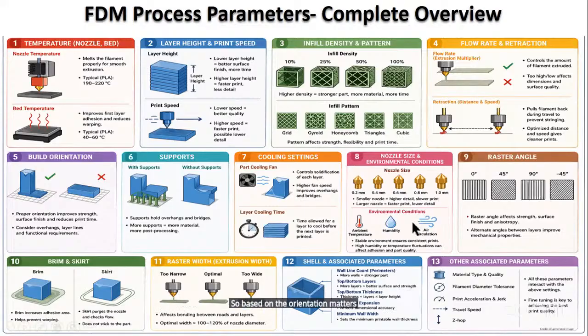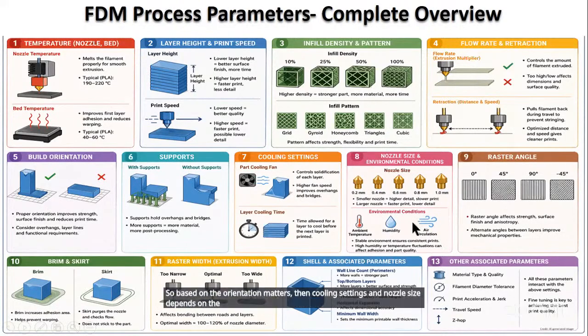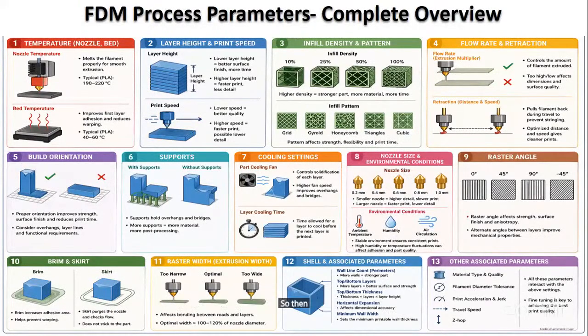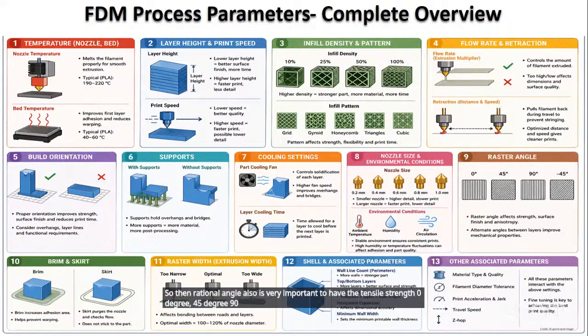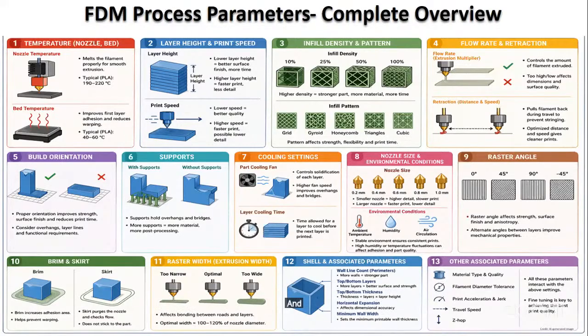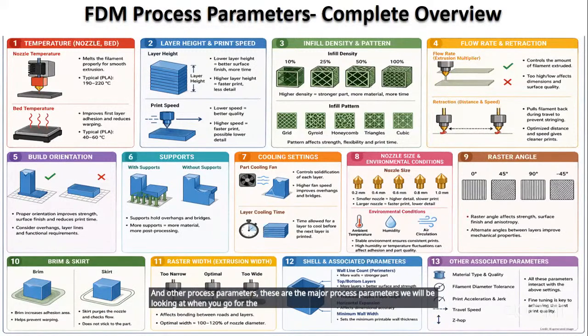Then cooling settings and nozzle size depend on the machine, right? It starts from 0.1, even lesser in micro printing. So 0.2, 0.3, 0.6, 0.8, 1, right? Within less than 1 mm, printers are generally available. Then raster angle is also very important for tensile strength: 0 degree, 45 degree, 90 degree. I have an example for that which I'm going to discuss. Then brim and skirt at the start of the printing, where we check whether proper printing is happening or not. And other process parameters. These are the major process parameters we will be looking at when you go for printing of the material.